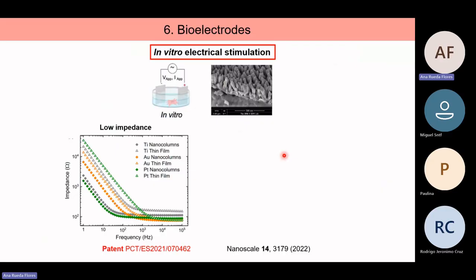Another application is for bioelectrodes. We would like to perform in vitro electrical stimulation, but I will show you just results in physiological media, without cells up to now. So what we are going to do is compare, in electrochemical impedance spectroscopy, the performance of nanocolumnar electrodes with electrodes of the same metal in thin film shape. So standard flat electrodes compared to columnar electrodes.